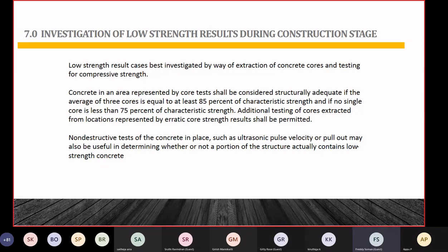Then we have to interpret it. As per ACI, the American Concrete Institute standard, if a particular column failed in the cube testing, then we want to go for core testing. Whenever the court or whoever appoints us, we go for a core test. In the core test, if we take a group of 3 cores, the average should be more than 85% of the characteristic strength. For example, if it was 40 Newton grade concrete, and a dispute came, the cube test failed at maybe 25 or something like that. When we took cores as a group of samples, the average should be more than 85% of the 40 Newton grade.